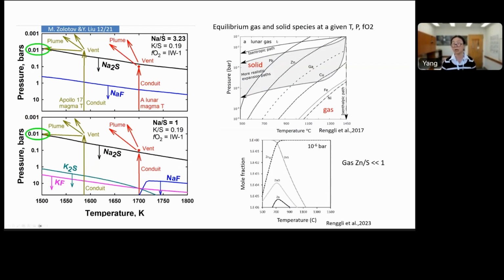and oxygen fugacity. There is no time to go into the detail of the plot, but basically the figure on the top shows, at a certain temperature and pressure for that element, whether it would be in the solid phase or gas phase. But this figure doesn't tell you what species it would be in. Rather, you use a plot on the bottom like this to show whether it's zinc sulfide or zinc metal. As you can see from both of these models, zinc is predicted to be mostly in zinc sulfide, but not zinc metal. So the observation of zinc metal is still not explained by current models.